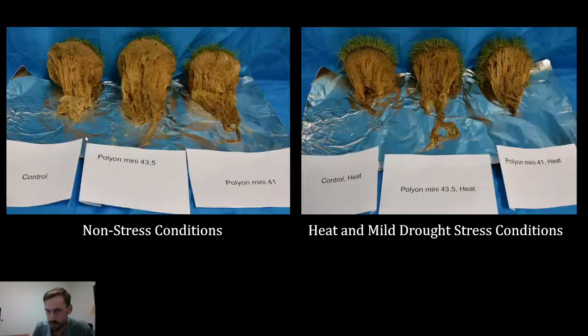But the shoots only tell half the story. Let's also look at the roots. And certainly on the non-stress conditions, as we would expect with creeping bentgrass, we had significantly greater root mass as a whole under the non-stress conditions, regardless of the treatment. But what was fascinating in this trial is that under the heat and mild drought stress conditions, we actually had the greatest root mass with the fastest releasing nitrogen material. So that's not necessarily what we expected at all, but lots of times with research, we find conclusions that counter what we would have our expectations be at the beginning of the trial.